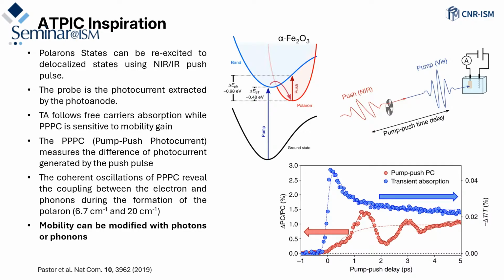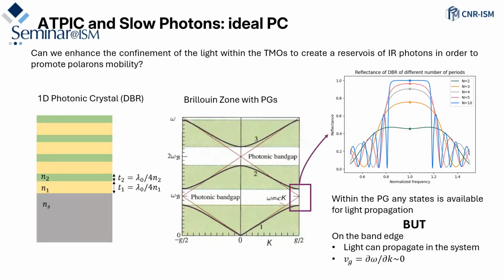Considering the photocurrent, when we also use the push, so just to excite the polaron more to the conduction band, they observe this oscillating behavior, which is due to the coupling of the electron with the particular phonon that they measure. But the main idea was that we can, in principle, modify the mobility of the material with photons and phonons. So the main idea of the project was, can we enhance the confinement of the light within the transition metal oxide to create a reservoir of infrared photons in order to promote the mobility in the material?